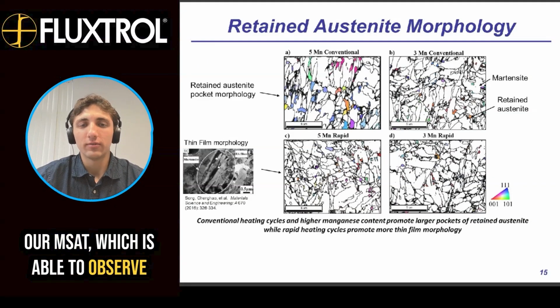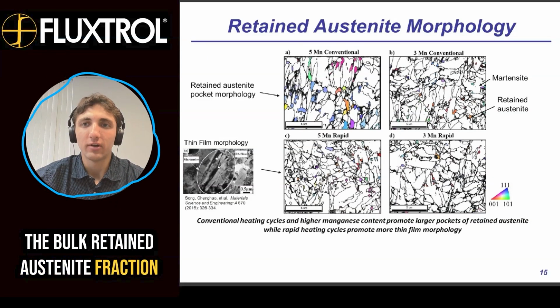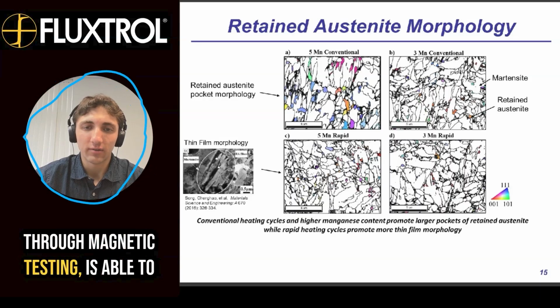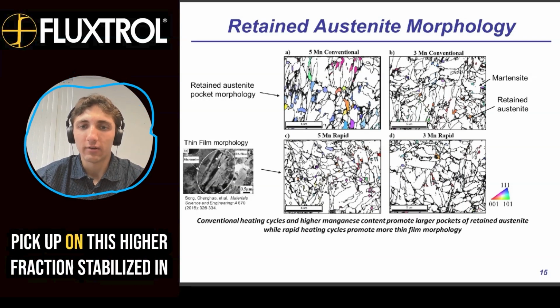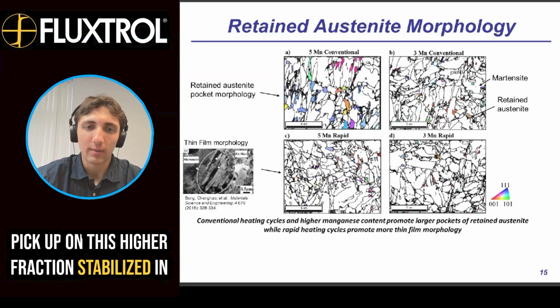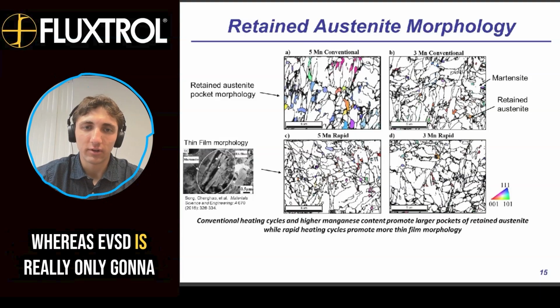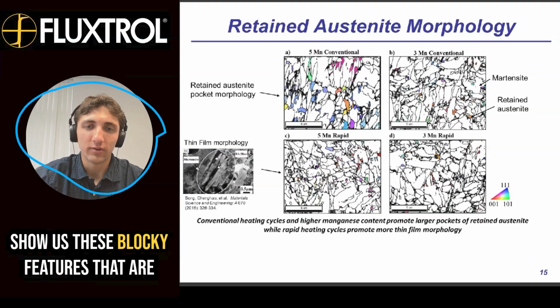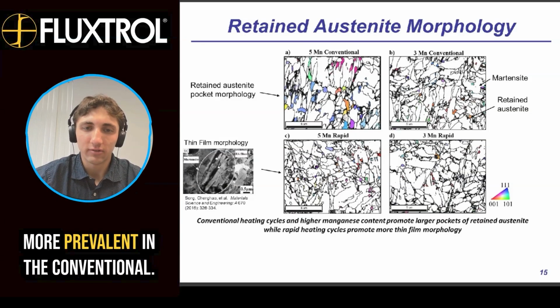And this could be the reason we're seeing a decreased fraction predicted by our scan, whereas our MSAT, which is able to observe the bulk retained austenite fraction through magnetic testing, is able to pick up on this higher fraction stabilized in the rapid condition, whereas EBSD is really only going to show us these blocky features that are more prevalent in the conventional.